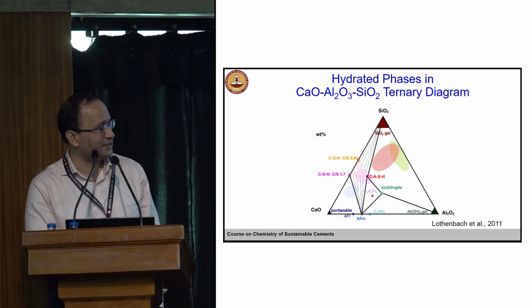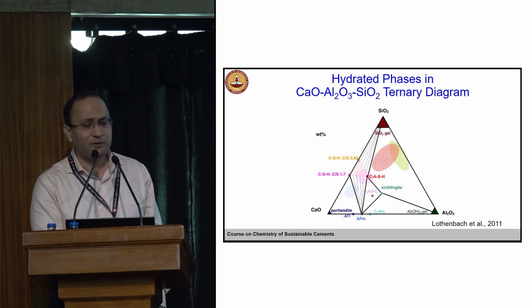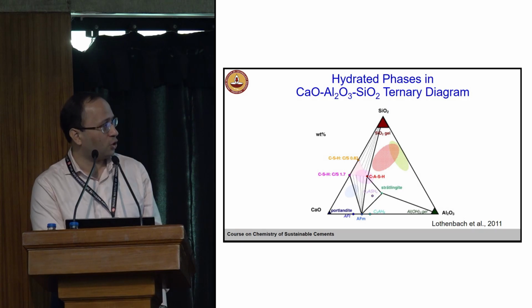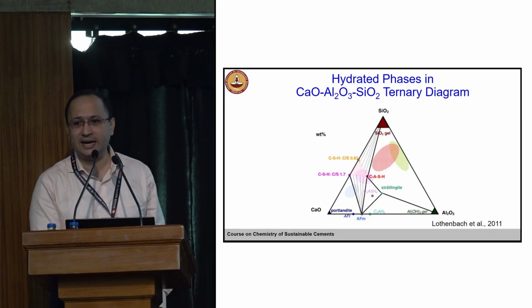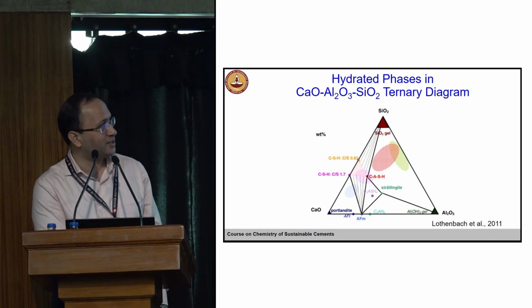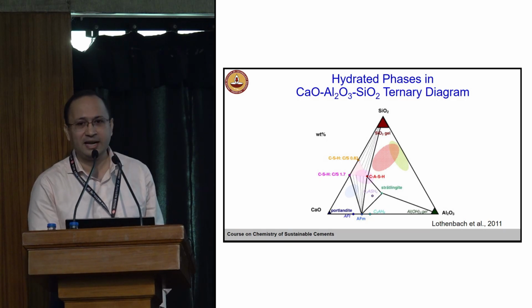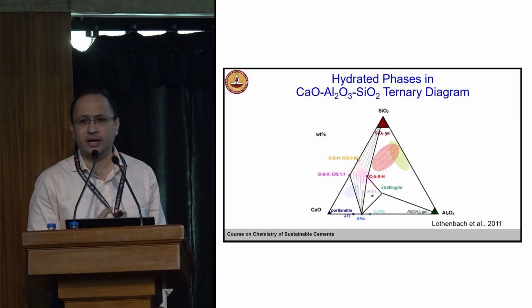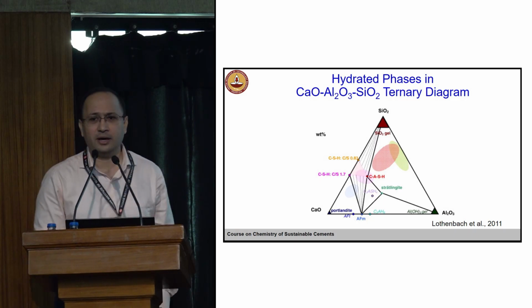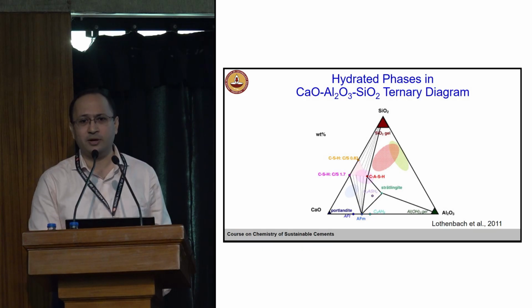Then you have a lot of phases on this line connecting CaO and Al2O3, right? AFt, which has more calcium. Then you have AFm, which will have more alumina. So you see, as you move from the calcium corner to that corner, how the phases are changing, right? Now, if you have phases like calcium aluminosilicate hydrate, let's say CSH incorporating alumina, you are somewhere here, right? Then some phases like stratlingite can also be found here. So depending on chemistry, you will have different types of phases, and thermodynamics will also govern what kind of phases will form, right? If you have only calcium oxide and alumina, you are never going to form CSH.